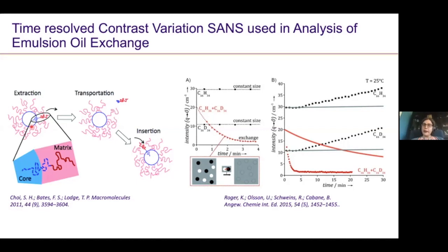So by tracking the intensity as a function of time, they could actually measure the transport of a single polymer chain as it leaves one of these micelles, goes through the solution, and then inserts itself into a different micelle. And they can track these molecular systems as a function of time.